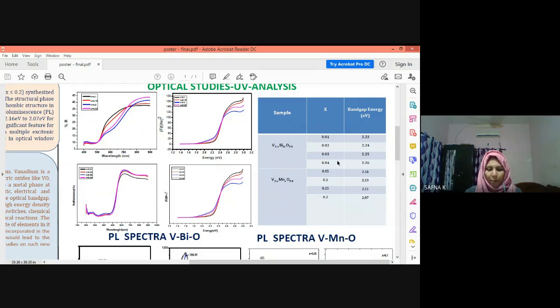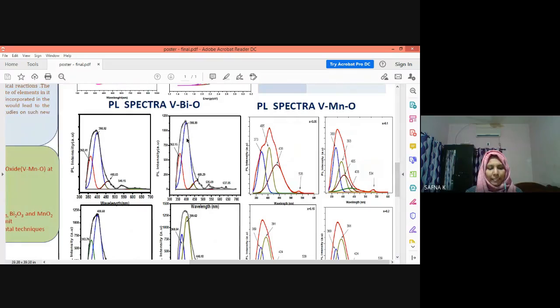And this is the estimated bandgap energy using the Kubelka-Munk function, and with increasing mole fraction, the bandgap energy of the VBIO system increases, which can be explained using the Moss-Burstein effect. While in the VMNO system, as x increases, the bandgap energy decreases, since as free carrier concentration increases, the bandgap widening is counteracted by a narrowing caused by the correlated motion of charge carriers and by their scattering against ionized impurities. And this represents the PL spectra of the prepared samples at room temperature.